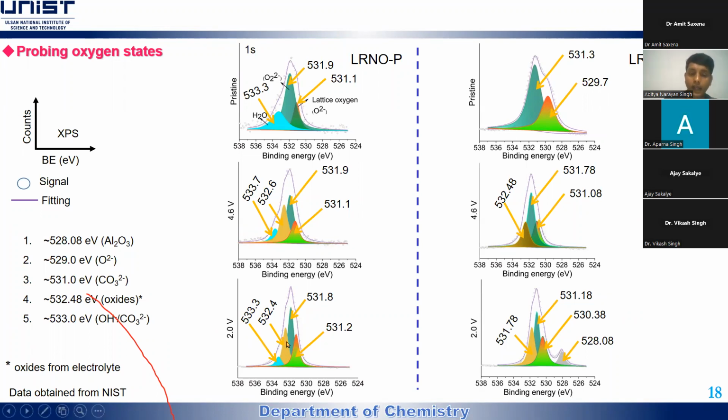But in the case of nickel, when we discharge it back to its original state after charging, we find that oxygen has been released from the lattice structure. It means that despite nickel doping, it cannot suppress all the oxygen from leaving the crystal structure.